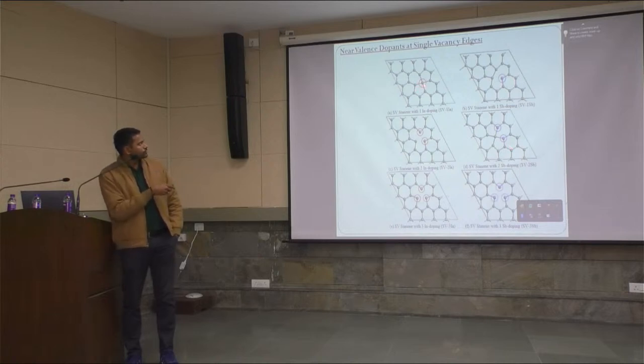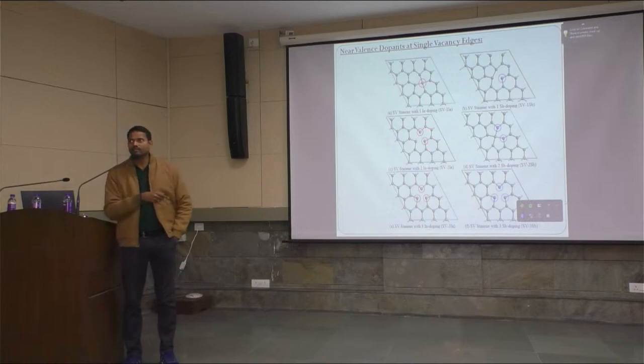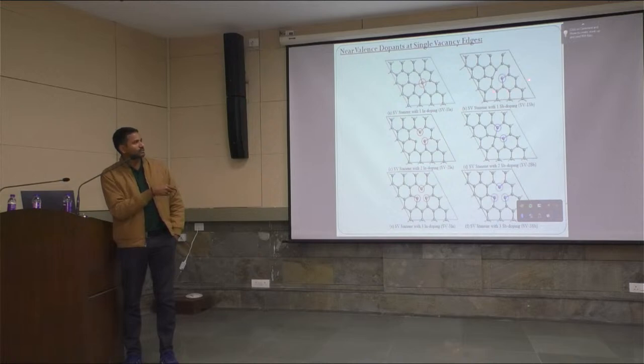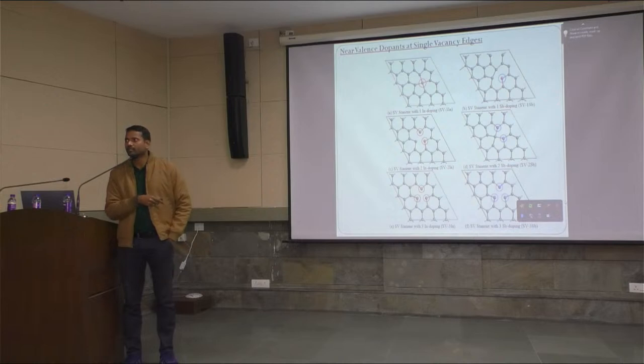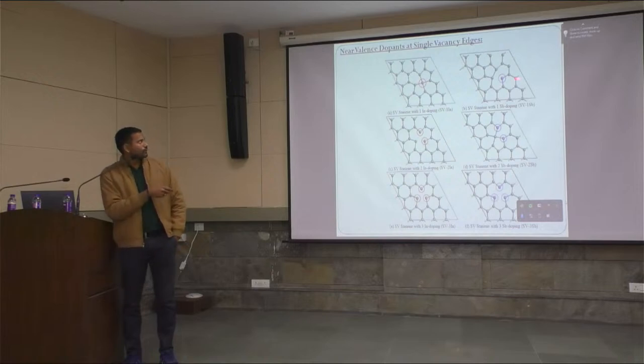And we have seen that as we position more dopants at the edges, the stability is increasing. This can be attributed to the elimination of dangling bonds by positioning these dopant atoms. And we have observed that antimony offers better thermodynamic stability in comparison to indium in stanene, because when we position antimony, the antimony can offer a lone pair, but indium cannot offer a lone pair. So we think this is the reason we are getting better stability for antimony in comparison to indium.